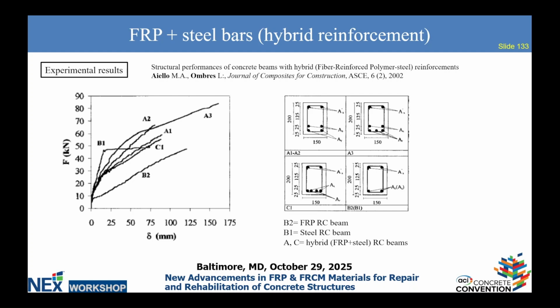Now, what we have to consider here is that in this particular aspect, if you look at A2, A1, A3, it's not just the amount of reinforcement, but also the position and the diameter. So you can basically play in a way that you want to reach the maximum curvature and at each reach the balanced failure, right? That will be the best in terms also of achieving the maximum ductility.